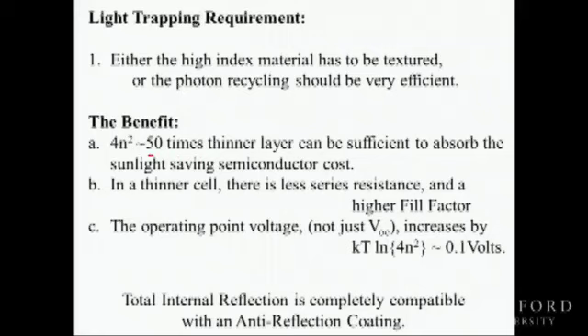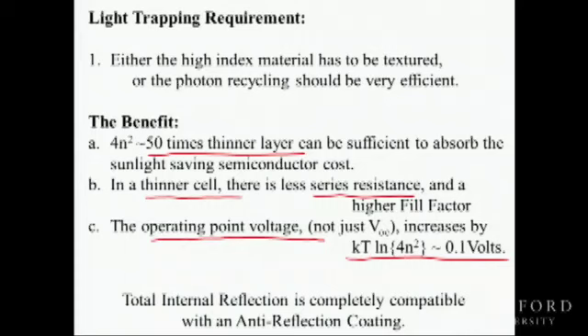A thinner layer, the carriers don't have to go as far, so there could be less series resistance. But even more importantly, the operating point voltage goes up. And this is a little bit subtle. It goes up by kT natural log of 4n squared. I'll show you where that comes from later. That's a lot. A tenth of a volt at the operating point is a huge improvement.